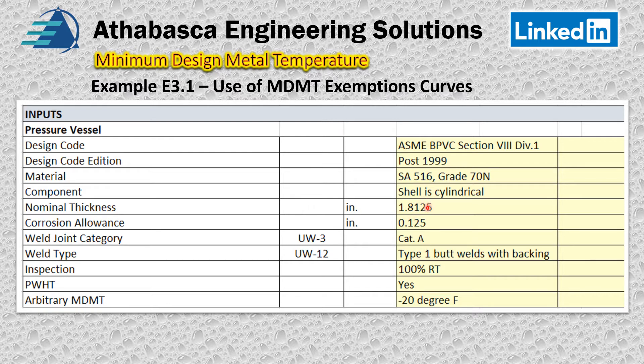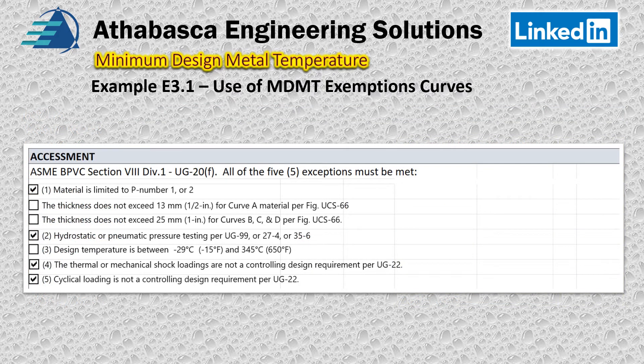It's a UW-12 Type 1 butt weld with backing strip, subject to 100% RT and post-weld heat treatment. When I look at that thickness, it's likely required because of the code. The arbitrary MDMT set is minus 20 Fahrenheit, or minus 29 Celsius. As mentioned earlier, we will look at the exemptions found in UG-20(f) as the first step. There's a table in Section 8 that goes through all of the steps and figures.